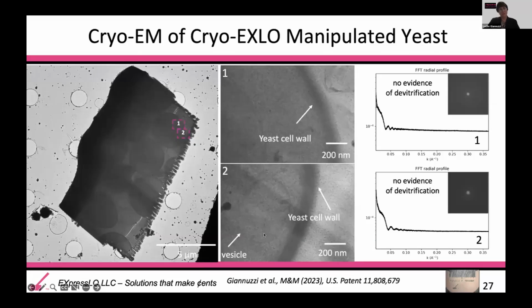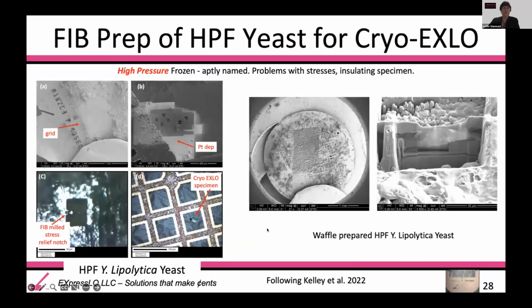Turns out that the FIB process itself for high pressure frozen samples, as people that are doing this can attest, high pressure frozen yeast is definitely, or high pressure frozen samples for that matter, is aptly named. These high pressure frozen samples are highly stressed. They're highly insulating. So our first attempt of this was with a high pressure frozen sample with several hundred microns of sample in the middle of a planchette. We had problems with